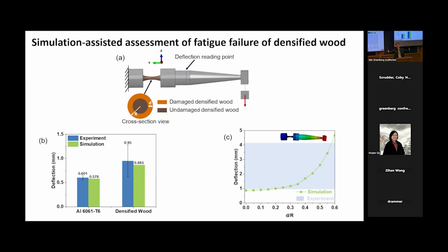Because we run this over a very long time, there were certain times, like during the night, when nobody is there. So when the wobbling displacement of the sample exceeds the threshold, it cuts off the tester to protect everything. Otherwise, it flies everywhere. So that also defines the fatigue failure. Basically, the structure is not stable anymore, and that tells you that you should actually stop and unload this.